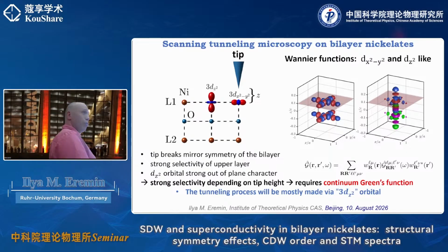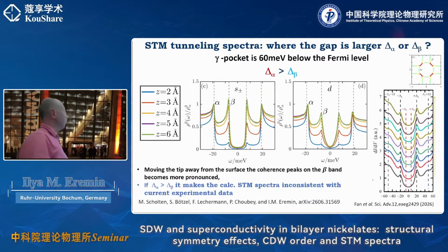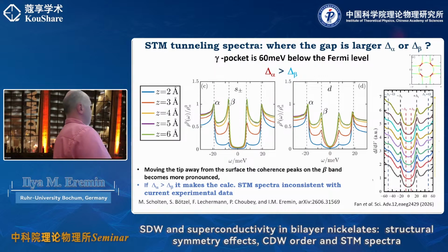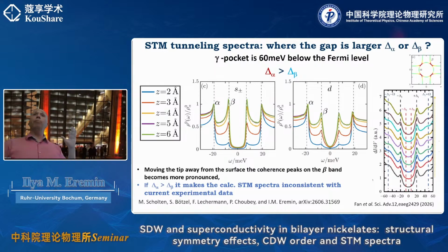When you do this, you realize that when you do STM in experiment, you will be mostly tunneling into the dz square orbital. And that immediately tells you that there will be some differences. First of all, even if you have dx square minus y square symmetry of the superconducting gap imposed, it will sometimes be hard to distinguish between s and d wave, simply because tunneling occurs via the z square orbital, and the contribution of the nodes, which is exactly where the main part comes from the dx square minus y square orbital, will be suppressed. So that's somehow bad news.